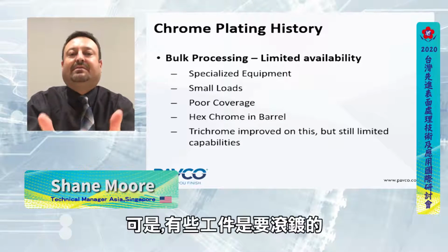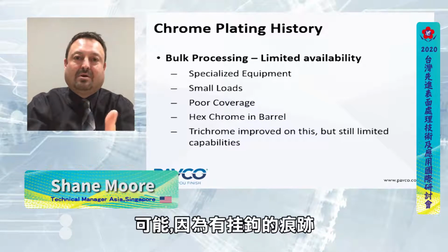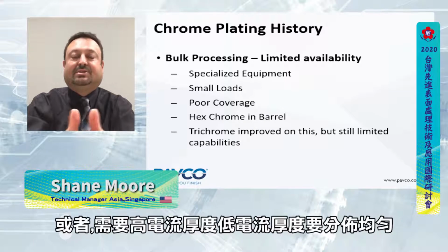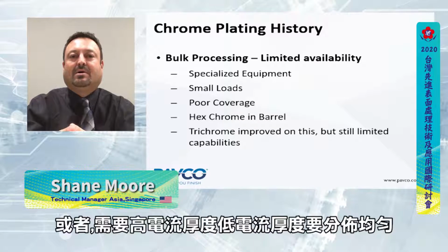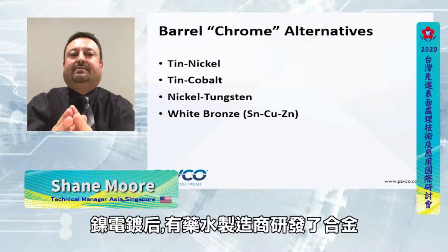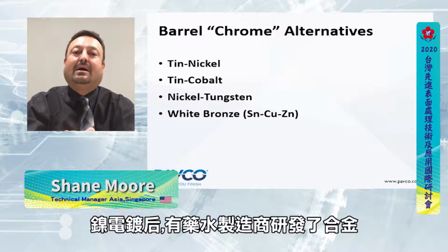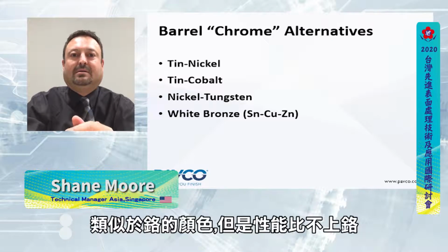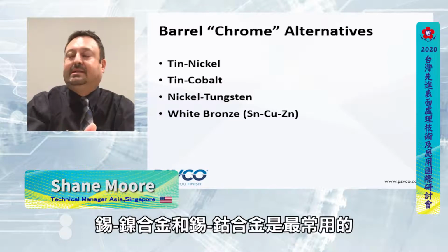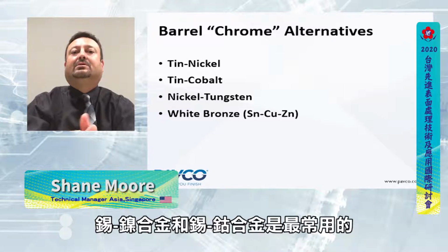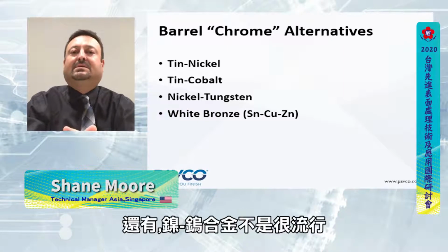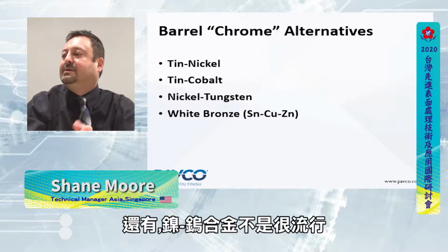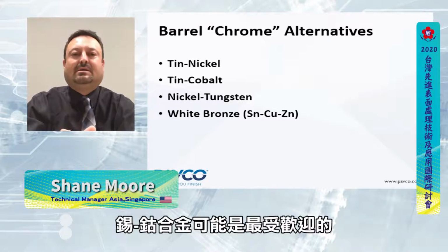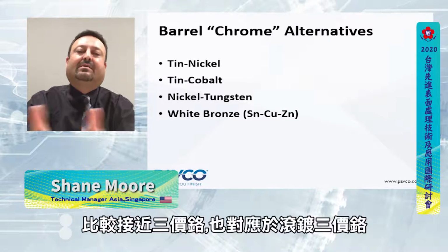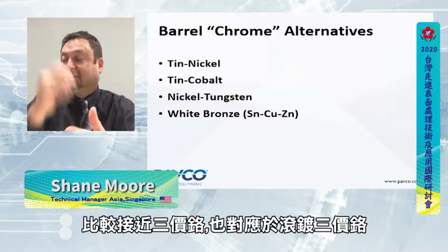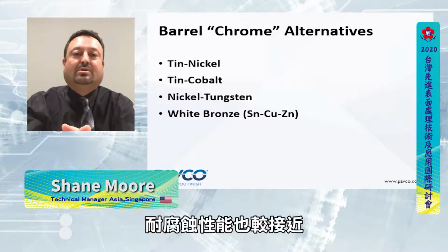So there are parts that have to be barrel plated, either because they can't have any rack marks, or the thickness distribution from the high current areas to the low current areas has to be small for many different reasons. After the nickel, some of the chemical manufacturers had developed alloys that were similar in color to chrome, but lacked most of the other characteristics of chrome. These were tin nickel, tin cobalt, which I'd say is the most popular that I've seen in the field. There's also nickel tungsten, which isn't very popular, but it is available, and white bronze. Since tin cobalt is the most popular one, that's the one that I'll be comparing the trivalent chromium in the barrel to, as far as the characteristics, the corrosion resistance, and things like that.